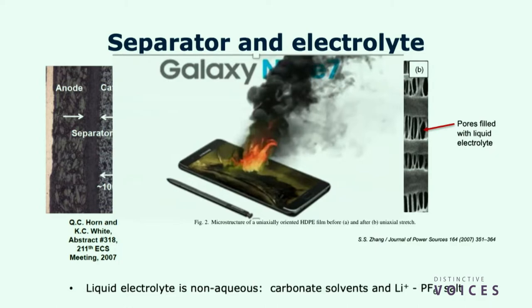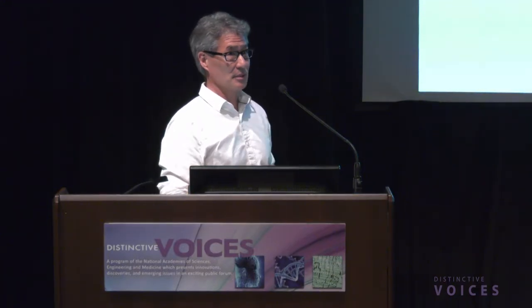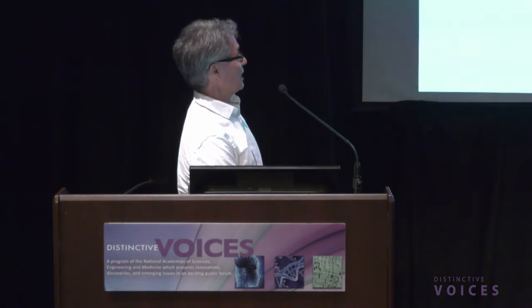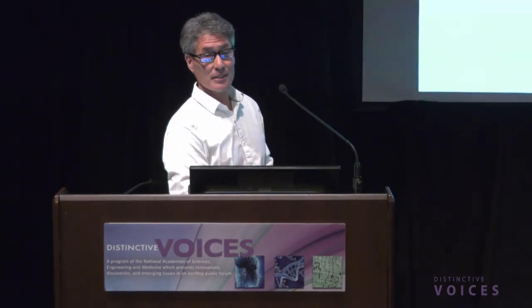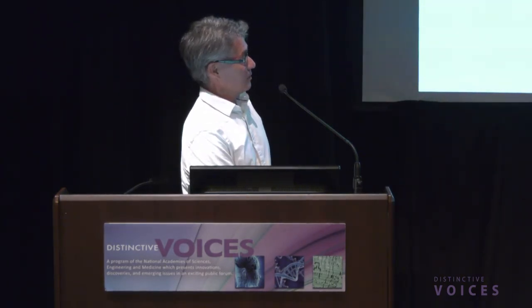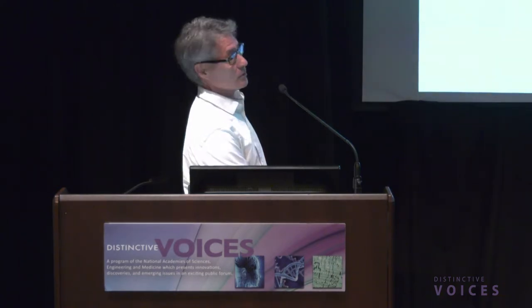But in the news, this was what Samsung did: they pushed the limits. They tried to make this separator as thin as possible to maximize the amount of active material, because the separator just occupies dead space. But when it got thin, they had short circuits, right? And that's what caused these fires. My understanding is that was about a $7 billion debacle, right? So they had to pay that much because they pushed the limits with regard to that separator.